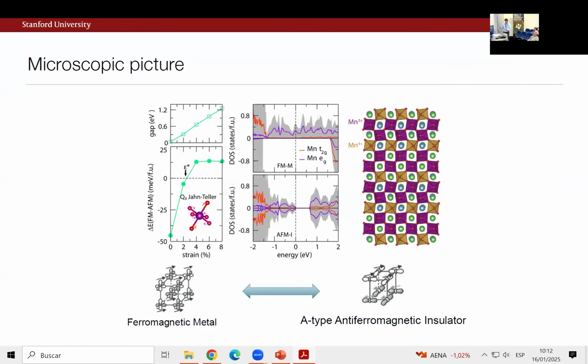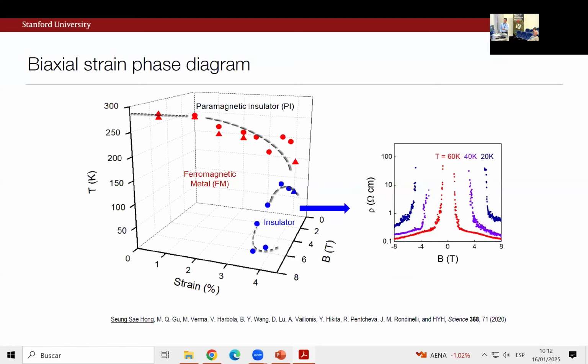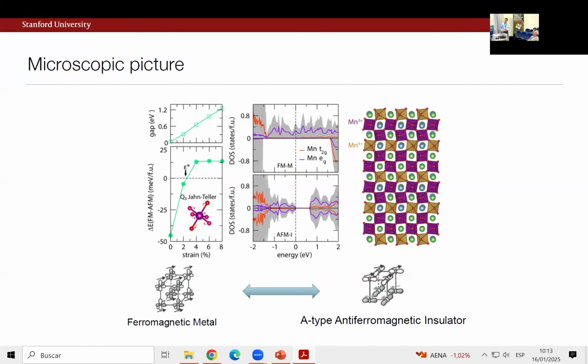So we were working with a number of computational theoretical friends on this paper. And the conclusion of the study is as follows. Again, qualitatively, maybe not a shock that this metal insulator transition has very much this flavor of this aspect of the phase diagram that when you have a ferromagnetic metal, this system is kind of trying to maximize bandwidth, minimize things like orbital splittings and so forth. Once you've decided to become an insulator, then Jahn-Teller effects, orbital ordering, these sorts of things kick in.